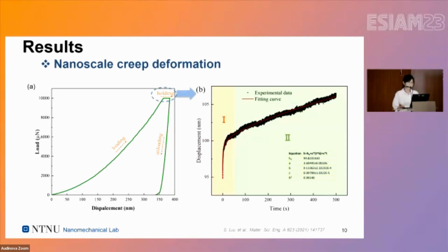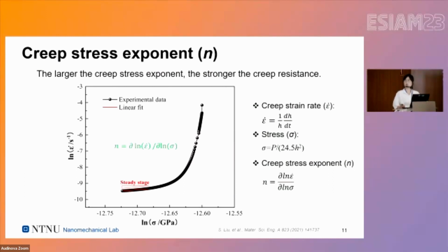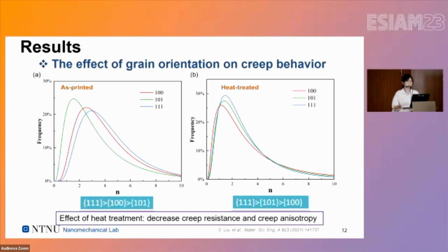From this stage, we can obtain an important parameter, which is called the creep stress exponent. It can be regarded as an indicator of the creep resistance. That is, the larger the creep stress exponent, the stronger the creep resistance. So we plot the distributions in different samples and different grain orientations. We found that in the printed sample, there is a strong grain orientation dependence. But in the heat-treated one, this dependence is not as strong as in the printed one. In both samples, grain 111 has the highest N value. That means that grain 111 has the highest creep resistance.